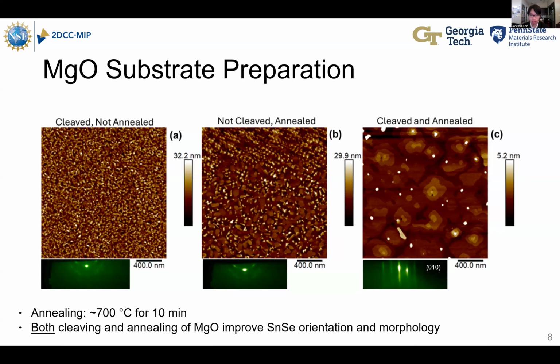Annealing, so going to high temperature. We're setting for 900, and we think we were getting around 700 degrees Celsius. We annealed that for about 10 minutes, and this allows us to burn off any of those excess carbonates or hydroxides that are left over on this face.